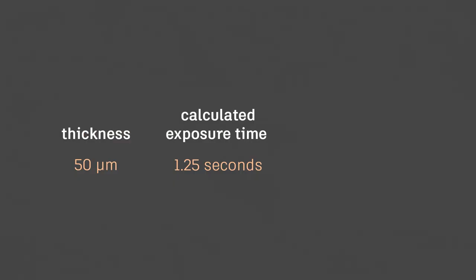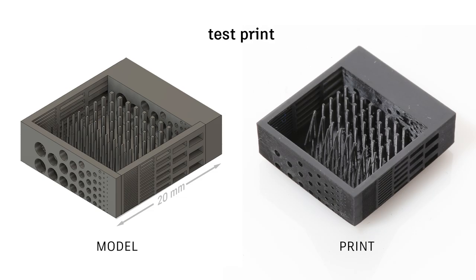So the exposure time we calculated is only the minimum time it takes to cure a film. In practice, for the layer to fully adhere to the previous layer, the exposure time is usually between 20 and 40% more time than is specified on the graph. You can figure this out with a handful of test prints.